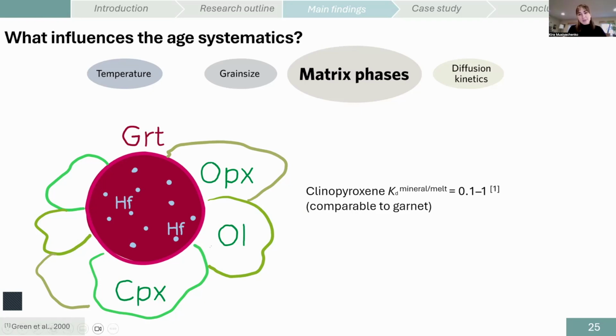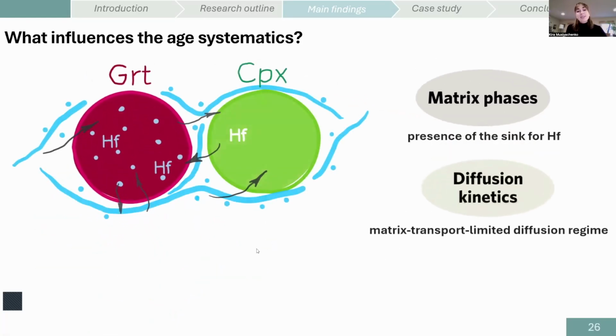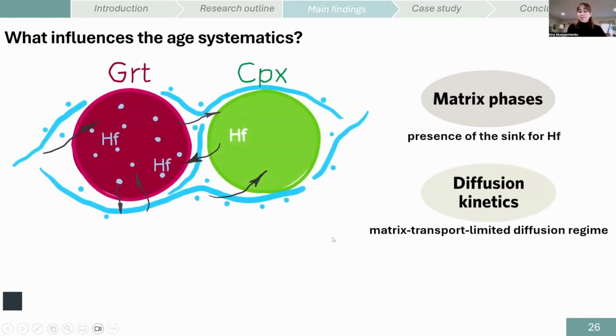That means that we're missing something, and that something is this last factor to consider, the diffusion kinetics in the mantle. The mantle is really, really dry. So even if the distribution coefficients between the phases would allow the exchange of hafnium between them, there is still this energetic barrier to transport the hafnium from one phase to another. That kinetic barrier can be suspended if we have a fluid or a melt on the grain boundaries that would facilitate this exchange. And you know what?